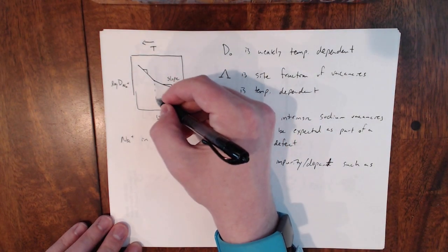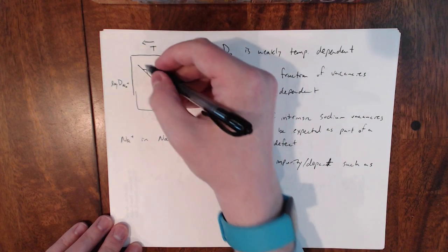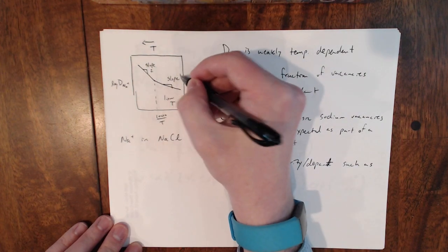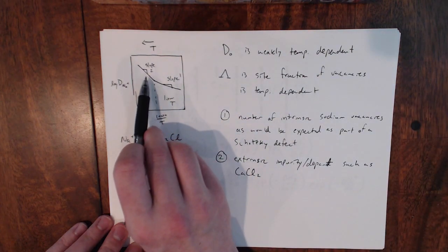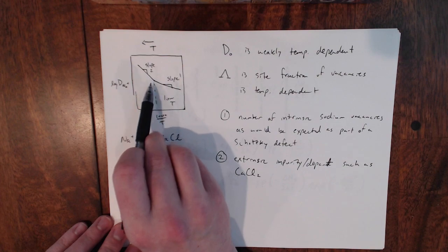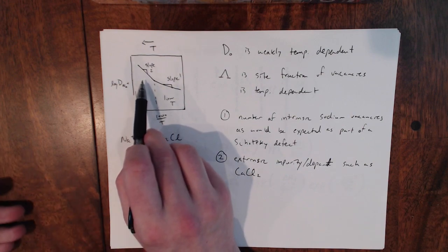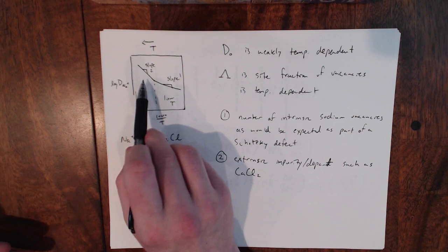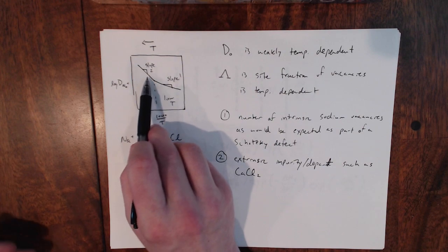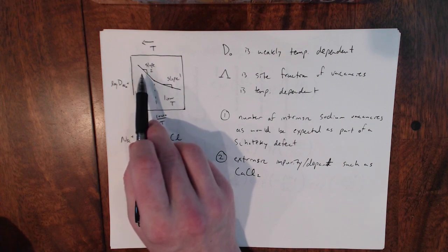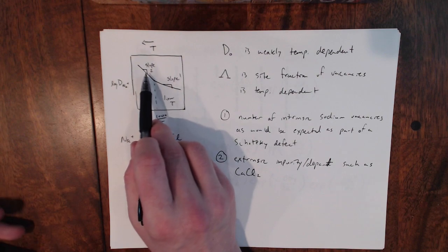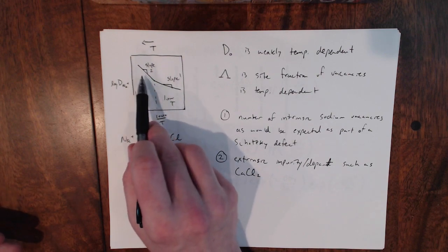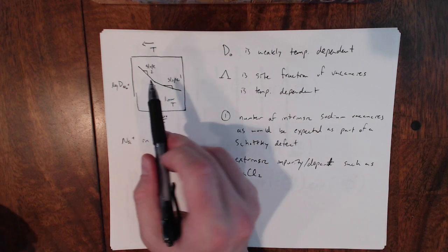But then at a certain point, there's kind of a crossover here, and above that we see a different slope. So I'll call this slope 2, and this one slope 1. So slope 2 here at the higher temperature, right? So now we have the extrinsically doped part of the material. So that doesn't change. How much calcium we added doesn't change. But we've increased the temperature, right? And so that activates those Schottky defects. And so the slope increases, and it accounts for both the migration and the thermally activated based on the site ratio. And so we have a different slope that occurs there. And so that's how we can sort of explain these different variations in the slope here.